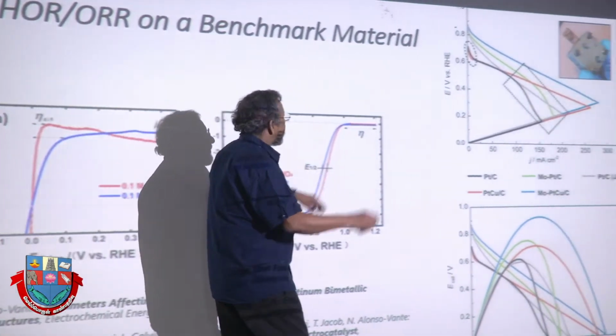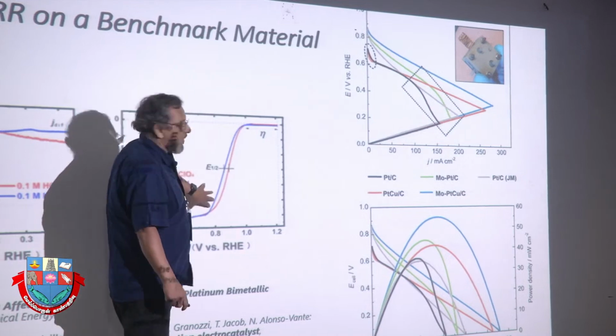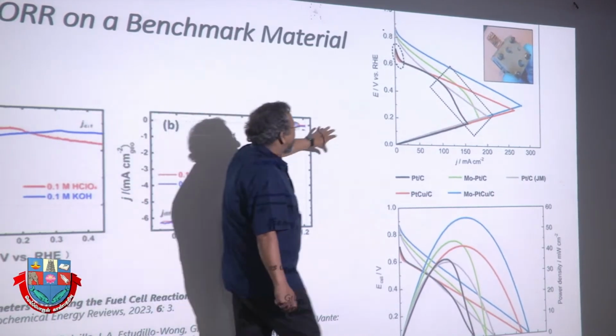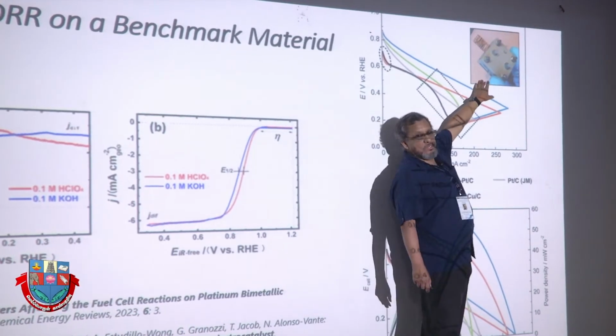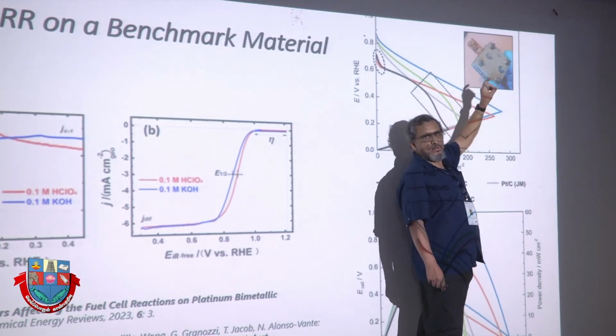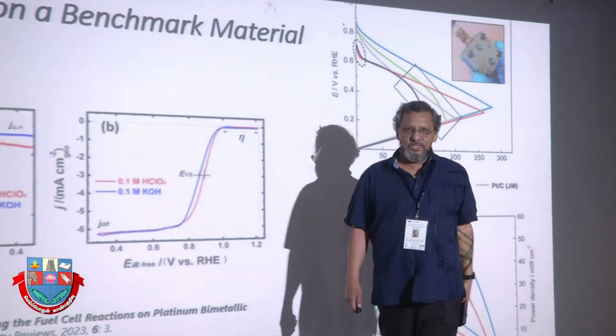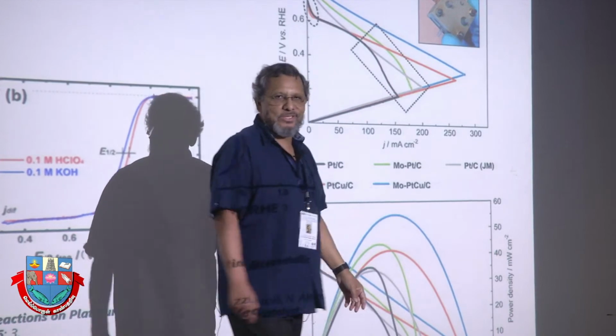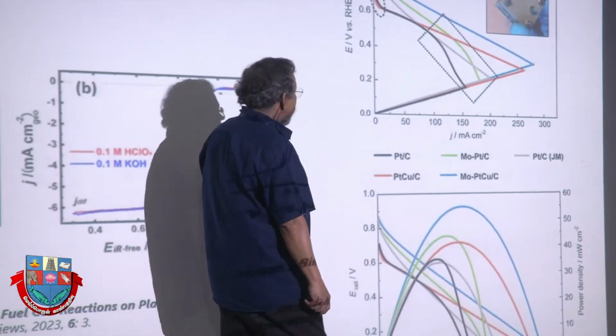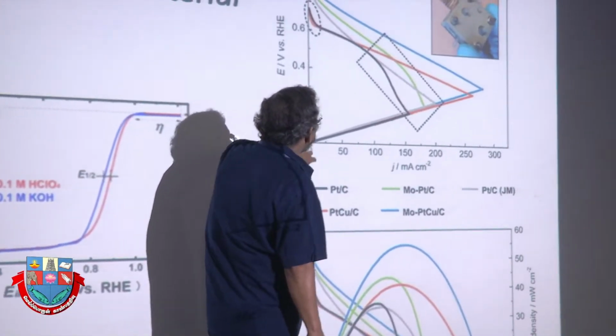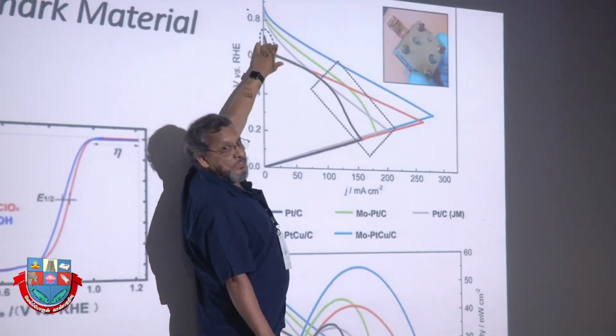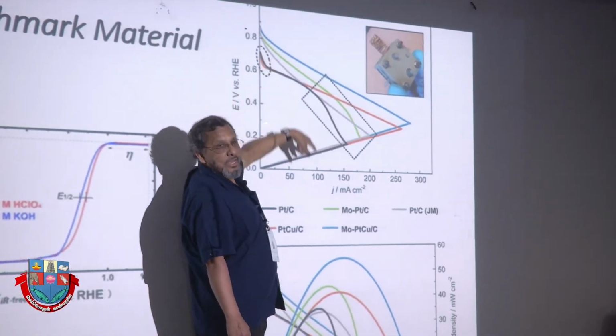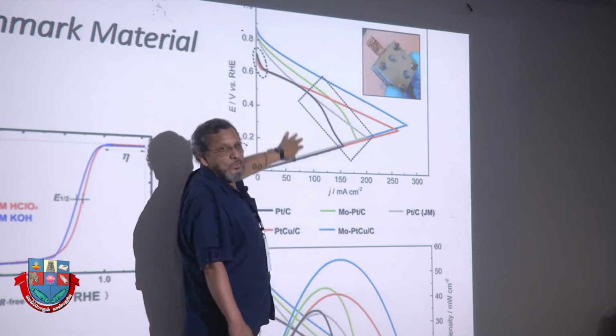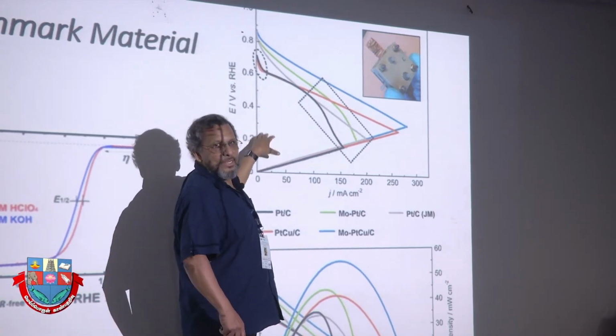We worked some time ago with this problem. And see, there is a very interesting system, the so-called micro fuel cell, where we use a platform in order to test many materials in a very short time, avoiding the use of a membrane electrolyte. And the beauty here is that you can measure the anode and the cathode of the fuel cell at the same time, so you see which electrode is limiting with the applied electric potential.